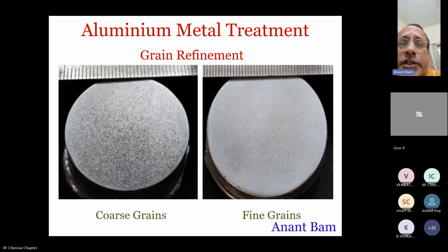You dip this finely machined or finely polished specimen for 20 seconds in Tucker's etch and wash it immediately. Allow it to air dry. Do not wipe by hand. If necessary, pat it, clean it, dry it by using a tissue paper without wiping.